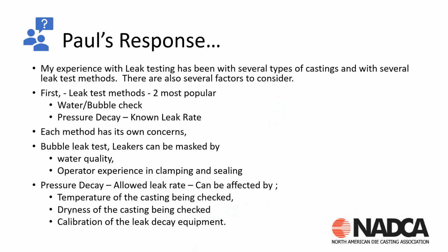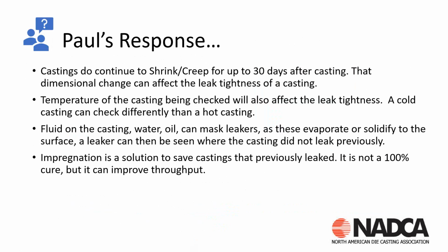On the pressure decay, the allowed leak rate can be affected by the temperature. Temperature is extremely important. Hot castings check differently than cold castings. Then there's the dryness of a casting. So if you're using a pressure decay and the casting just came out of a machining center and it still has wetness on it, that wetness from the machining operation can mask the leakers. And then the calibration of the leak decay equipment. So how often are you calibrating? Are you checking known leakers to validate the equipment? So those two different types of leak checks can be done.